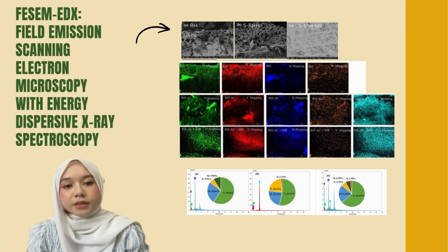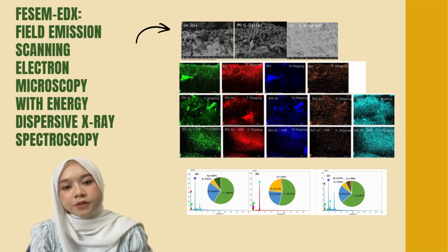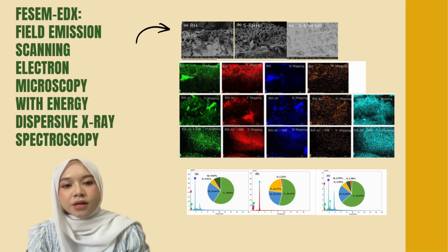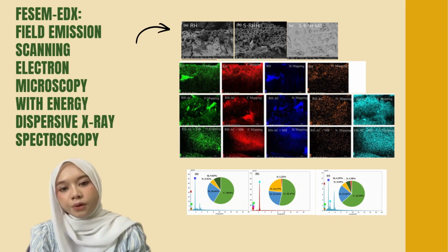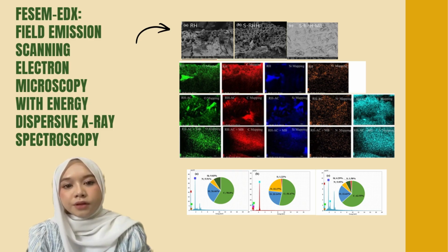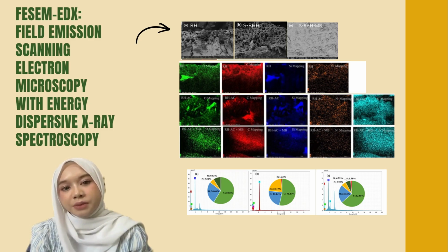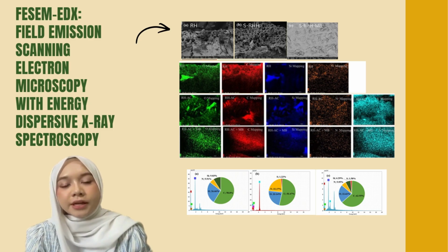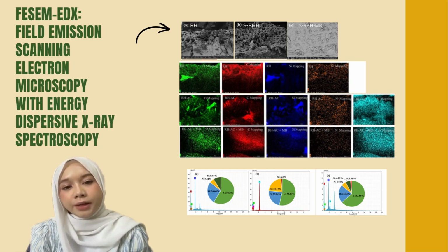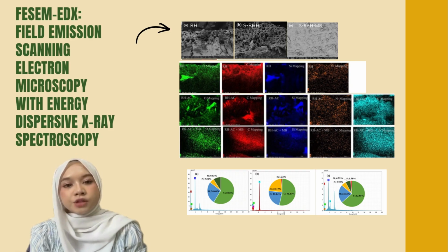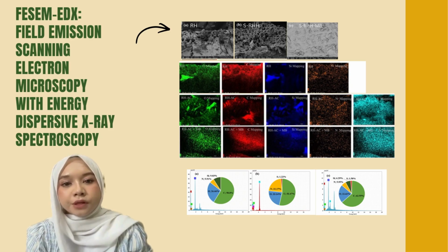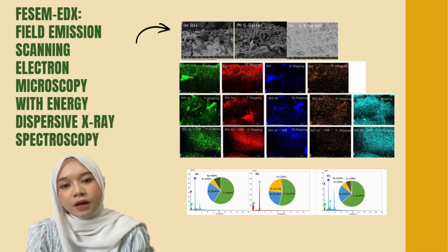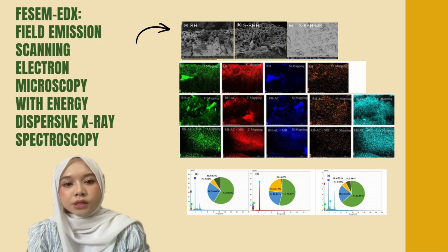Morphological and elemental analysis were performed using FESEM-EDX. Raw rice husk shows a heterogeneous structure and distribution of big pores. Meanwhile, sulfonated rice husk exhibits bigger pores, fissures, and indentations, validating the impact of carbonization with H2SO4, which improved the mesoporous structure. After the adsorption, there is a decrease in porosity and development of a dense surface, which indicates that the dye was effectively adsorbed.